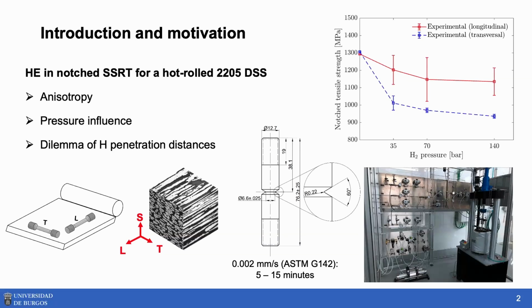A key point here is that we have a slight influence of the pressure after higher pressures. So we expect a kind of saturation of some interface or defect, as we will discuss later. Another point is the dilemma of the hydrogen penetration distances, because as you probably know, the diffusion in this kind of steels is very, very low. For the testing times that we obtain following the crosshead displacement rate of this standard, tests are very short, maybe less than 5 minutes for the strongest embrittlement. So for this very short penetration, why are we obtaining this relatively high embrittlement?